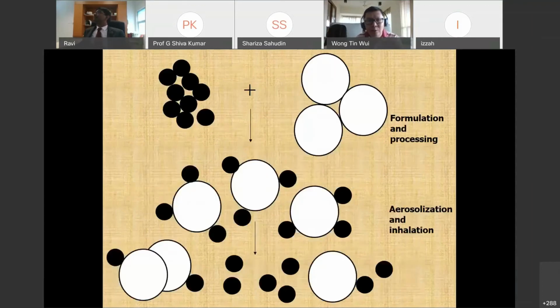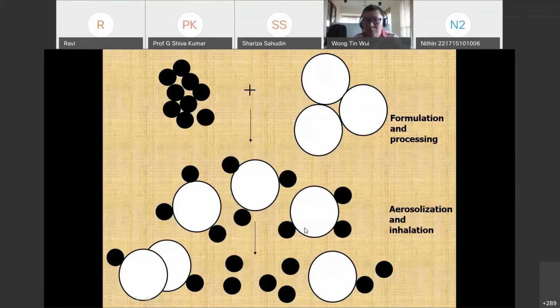Now let's take the hypothesis that we have derived. You can see that nanoparticles alone, due to the small size and high specific surface area, tend to be aggregative. Likewise for micro-scale particles, because they are only a few micron in size, they are cohesive and aggregative. So by blending both in a specific weight ratio, you will have the nanoparticles absorbed on the surfaces of the micro-scale particles. Note that once the nanoparticle is absorbed onto the surfaces of the micro-scale particles, the aggregativeness of the nanoparticle is reduced. And the nanoparticles sitting on the surfaces of the micro-scale particles can also act as a glidant, thus preventing the microparticles from aggregating with one another, right?